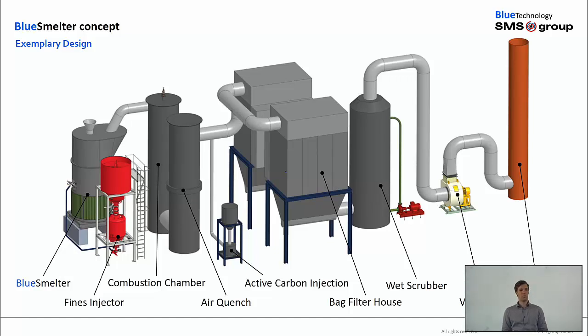How do we treat the scrap? We developed the Blue Smelter, which is a very intelligent smelting solution. This smelter takes the scrap and combusts the organics that come within the scrap, transforming them into heat. That means the smelting process, which smelts the mineral components and the metals, separated into a metal phase and a slag phase, is completely autothermal. That means we do not need any additional fuel or energy to run the process. Once started, the process fuels itself.